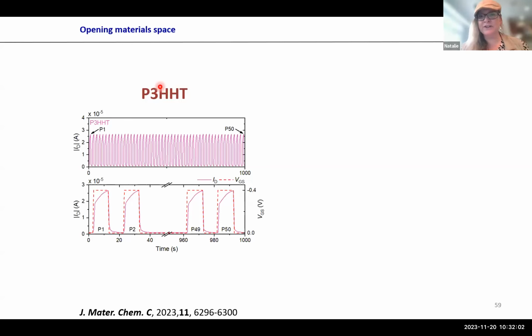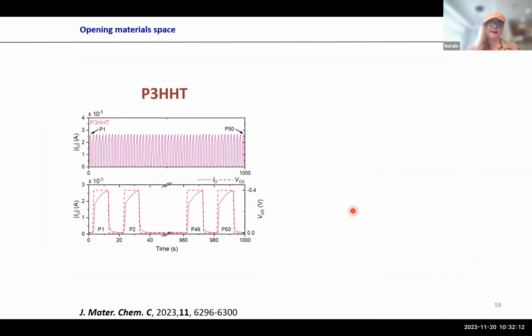This was now in an electrochemical transistor, which is very similar. So here we have essentially only a gate, one electrode. If you now also have a source and a drain, you can make electrochemical transistors and do exactly the same. So you apply bias up and down, and when you apply the gate bias, you change the source drain bias, and if you cycle, because the material doesn't swell, I show that in the next slide, the material really behaves extremely well.